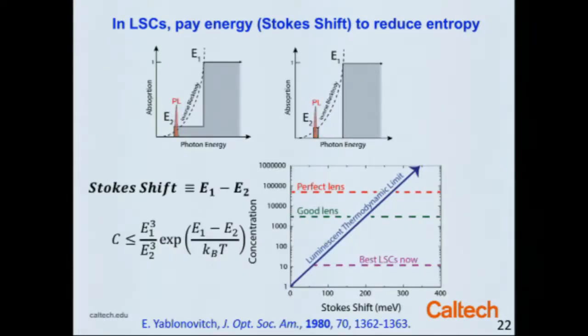This was first expressed by Eli Yablonovitch, and also by a fellow named von Roosbroeck, and ultimately Shockley, who pointed out that the concentration you can get associated with the downshifting of the photon from its absorption to its emission goes as a geometric factor of the ratio of the energies, times an exponential in the energy difference between absorption and emission. So you get an exponential concentration factor.